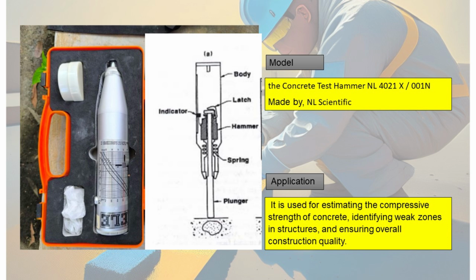The Schmidt rebound hammer works on the principle that the rebound of an elastic mass depends on the surface hardness of the material it strikes. Although there is no direct theoretical correlation between concrete strength and rebound number, empirical relationships have been established within specific limits. For instance, Kolek's research attempts to connect rebound numbers with hardness, measured by the Brinell method.